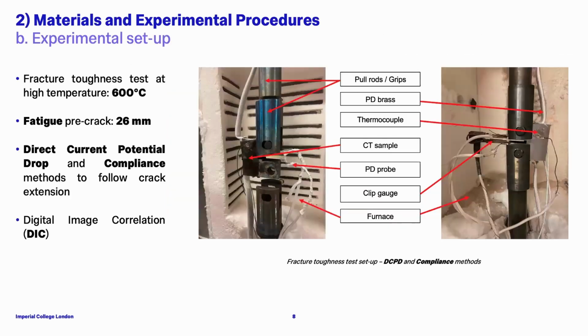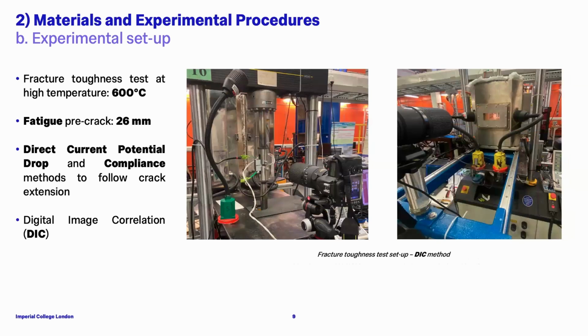The setup. Before any test, I pre-cracked all my samples by fatigue to a crack length of 26 millimeters. And I used basically 3 methods to monitor the crack extension during the test. First, the DCPD method, so direct current potential drop method, then the compliance method. And finally, I did some digital image correlation analysis using a camera, taking pictures through the window of the furnace. Only one camera has been used, so it will be a 2D DIC analysis.